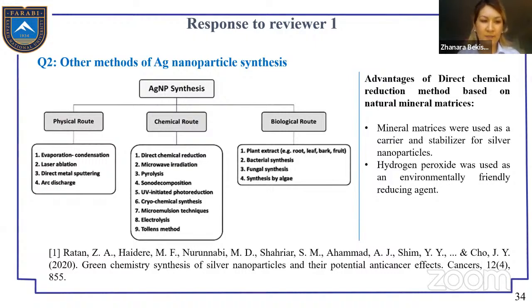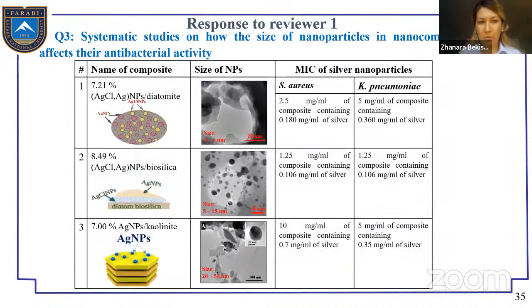For other physical methods, for example laser ablation, some equipment requires high pressure for obtaining silver nanoparticles. And in response to question 3, how the size of nanoparticles affects the antibacterial activity, we discussed that. This is an example of one concentration of the composite against 2 bacteria, and the bigger size, from 20 to 50 nanometers, is not as effective as the size of 4, 5 or 6 nanometers of silver chloride nanoparticles.